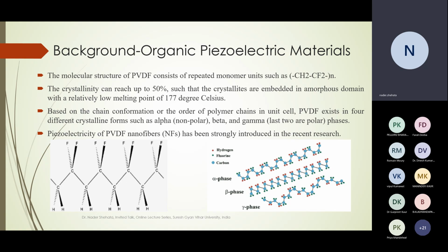And this material has a relatively low melting point. It differs according to the structure of PVDF, the size of nanofibers, impurity, and so on. In most applications or research literature, it has a melting point between 160 and around 180 degrees Celsius. In some applications, it could be considered an advantage, but in some applications, it could be quite a restriction for using this PVDF. Let's move deeper inside the crystalline structure. Based on the chain conformation of the order of these polymer chains, the PVDF could be found in different phases according to the right diagram.